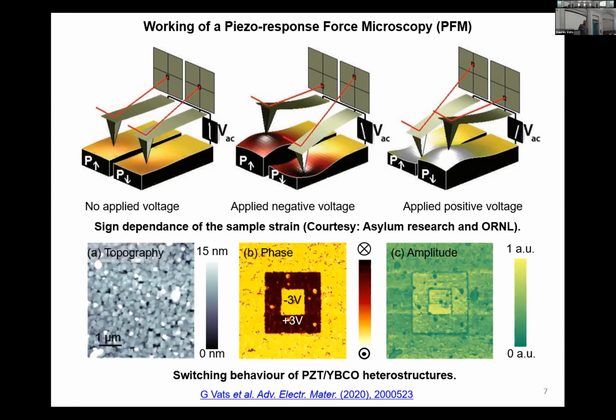For example, here I am showing you the domains in PZT/YBCO heterostructures. In figure A, you can see the topography, which is basically the surface. And then in figure B, you can see this phase image, where the color contrast shows domains, whether they are pointing up or pointing down. So for the rest of my talk, I'll be showing the phase images, and the only interpretation is the direction of the ferroelectric domains. That's what you can understand from the color contrast. At the same time, we can also acquire PFM amplitude, which is an indication of the piezo response of the material.